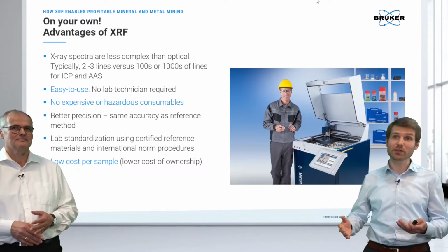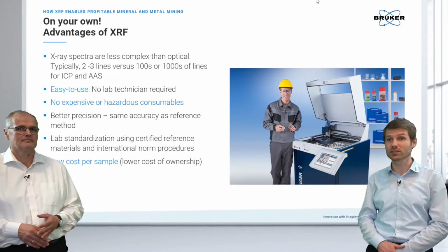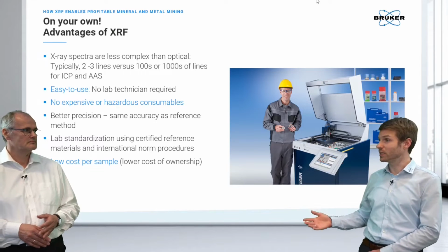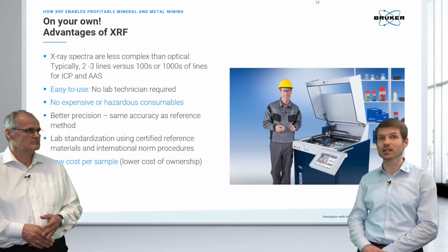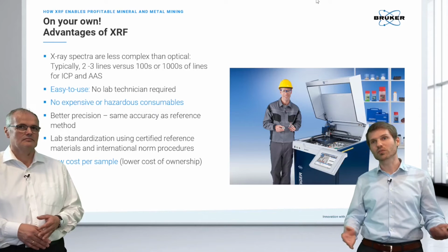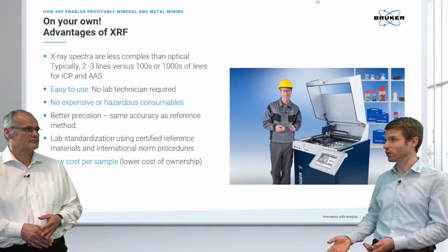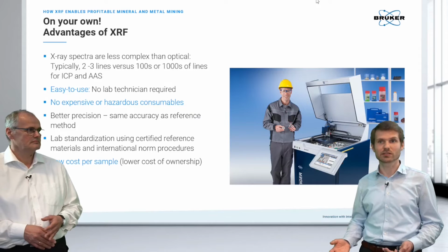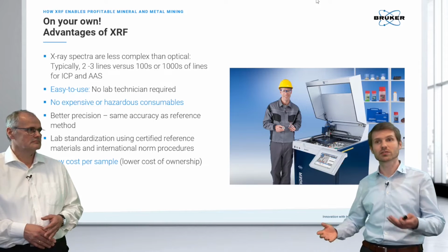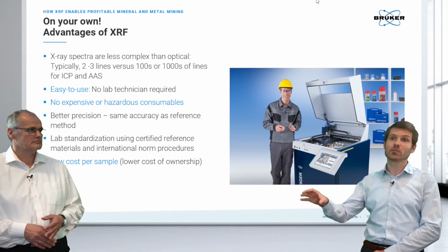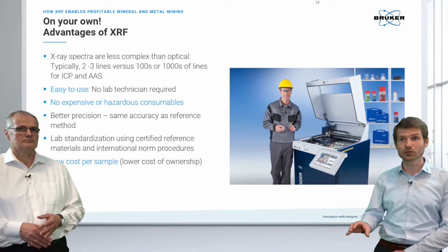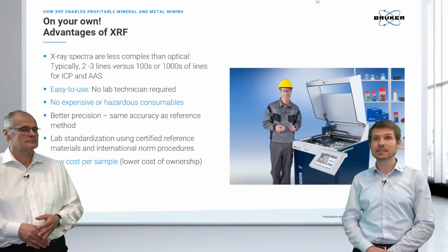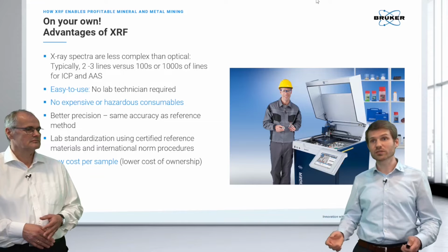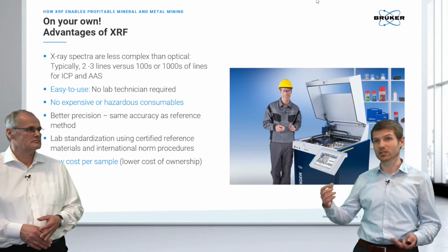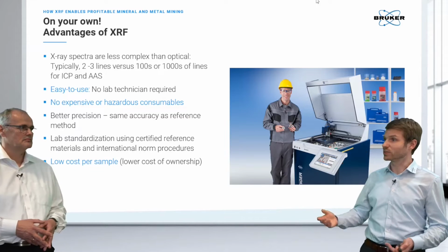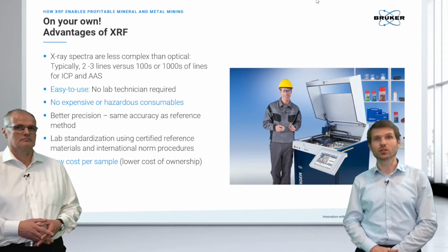And there are a few other things to keep in mind compared to other technologies. So other technologies are mainly ICP, so spectroscopic methods, and AAS. And here, one of the main disadvantages is that we have to first dissolve the sample. So we actually have to change the matrix, remove the matrix if you want. So we also have to dilute it differently for major elements and trace elements, different dilution ranges, so not everything at once. It is not as simple to use, so XRF is really, once it's calibrated, and calibration is not that difficult either, but once it's calibrated, it's really pushing the button and off you go.